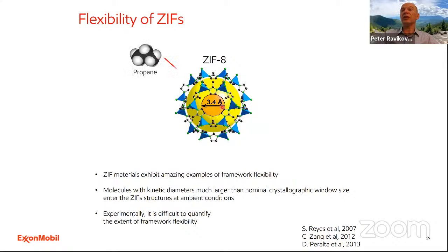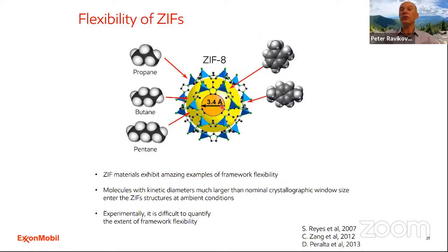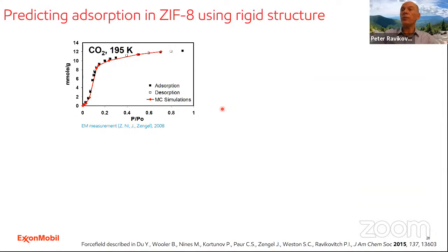Yet it can absorb many hydrocarbon molecules, and not only linear hydrocarbons, it actually can absorb xylene molecules, which are way bigger than the size of the window. So clearly the explanation for such behavior should lie in the flexibility. But is it always important to account for this flexibility? Actually, for predicting adsorption properties, it's quite surprising that you don't need to.